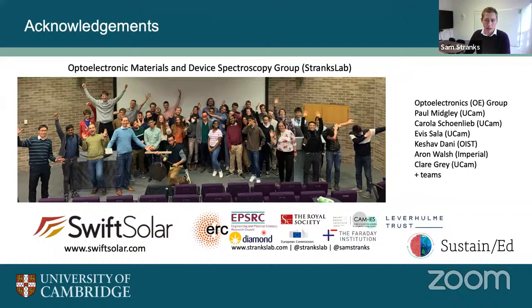One of the issues is we haven't yet been able to test them for long enough to know how long they last. And the second is that, as has also been the case for other PV technologies, there are failure mechanisms that only really come up multiple years into their lifetime. There are different failure mechanisms that we may discover as things go along. So we do have to continue to test these, particularly with accelerated tests, where we can really try and mimic many, many years of operation with elevated temperature, for example, or elevated sunlight levels, to mimic a very long lifetime. But there are still some issues to work out, hopefully over the next few years, that we'll be able to get rid of.